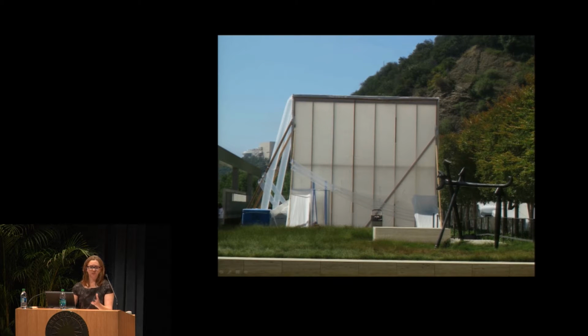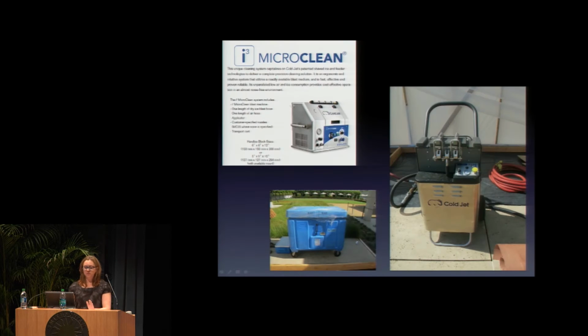This project was done in situ, and we built a tent around it with lots of ventilation, and we rented an i3 MicroClean, which uses the block, and Rosalind has described that system very well. In this case, we purchased a pellet form of carbon dioxide, and then using a kind of a block maker, you can actually make blocks to use for the MicroClean.